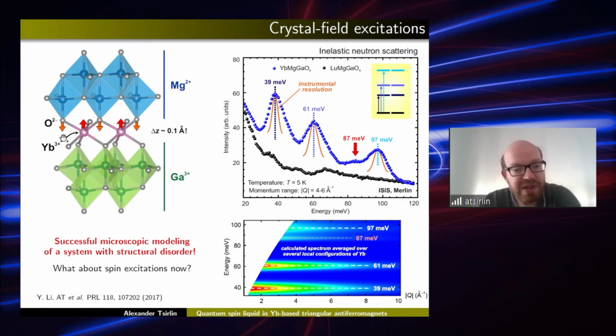So you may remember that the crystal structure, we had this magnetic layer of ytterbium, and then we had the slabs of magnesium and gallium in between the magnetic layers. And magnesium and gallium are mixed. So each of these positions is actually randomly occupied by both magnesium and gallium. At first, we didn't pay any attention to it because, okay, that's non-magnetic, so who cares? But in fact, they have the different charge. So magnesium is 2+, and gallium is 3+.